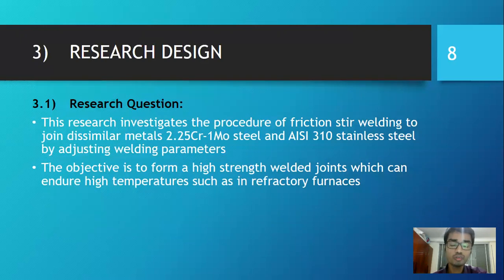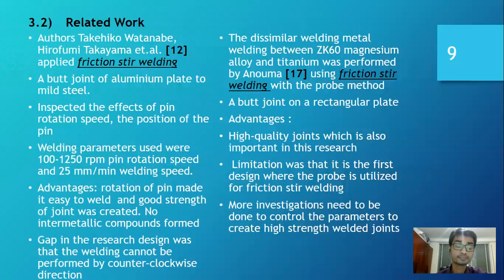And none of the researchers have used friction stir welding to specifically join these two dissimilar metals. So the related work has been done previously by researchers who have used friction stir welding. For instance, Watanabe has used friction stir welding to form a butt joint between aluminum plate and mild steel, and he has inspected the effects of pin rotation speed and the position of the pins.